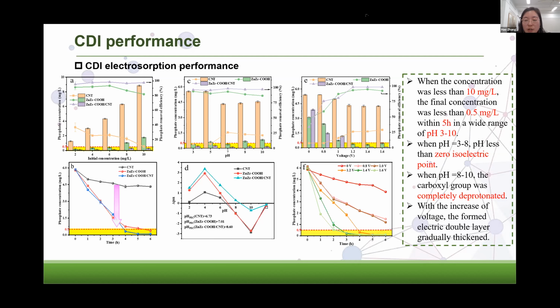And when the pH was in the range of 8 to 10, the carboxyl group was completely deprotonated, which can be used as a hydrogen bond receptor and can absorb phosphate. In figures E and F, we can see that the higher the voltage, the higher the phosphate removal efficiency. And with the increase of voltage, the formed electric double layer gradually thickened.